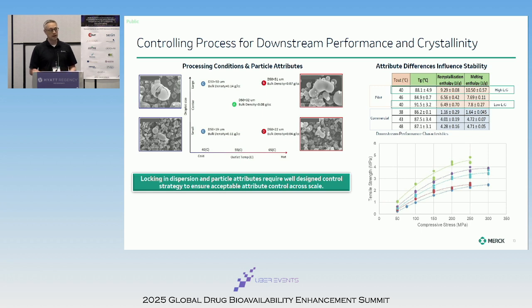And what we see is that as we work through the different processing conditions and ultimately drive towards different particle attributes, they can have impact on the ability to process downstream. So depending on the space in which you're processing your spray drying operation, your particles can actually become more compressible or less compressible, and that can have a marked impact on the ability to create the final tablet formulation, particularly if you're in a high dose case where not only are you pushing drug loading in the solid dispersion, but really trying to maximize the amount of spray dried intermediate that you have within your tablet formulation.